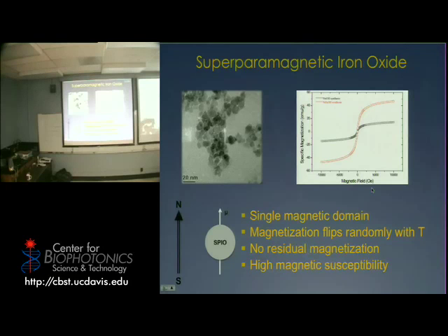It's called the saturation. So it's, in a way, how much magnetism you can put into the material. However, because they don't have any residual magnetization, when you remove the field, they just start spinning about by themselves because there's just a single domain. There's no alignment of different domains. They don't retain residual magnetization. It's kind of like an oxymoron if you want to say it that way, but you can magnetize them a lot, and when you take off the magnet, they go back about their business and they don't aggregate or have any properties like that.